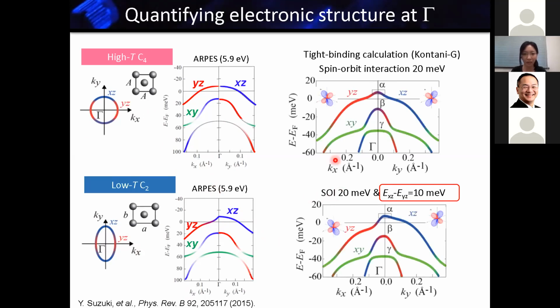Okay, and we passed our result to the theorists, and they tried to reproduce our ARPES result by doing a tight-binding model. And then they found that when they introduce an orbital order of 10 meV between this XZ and YZ, then they can nicely reproduce our ARPES result. So this is the result of the usual static ARPES experiment. From this experiment, we found that in the nematic state, there is a 10 meV energy difference between the XZ and YZ orbitals.